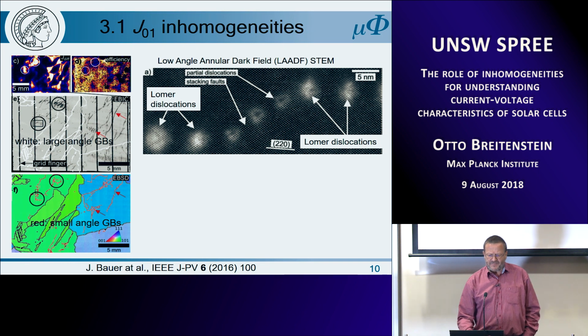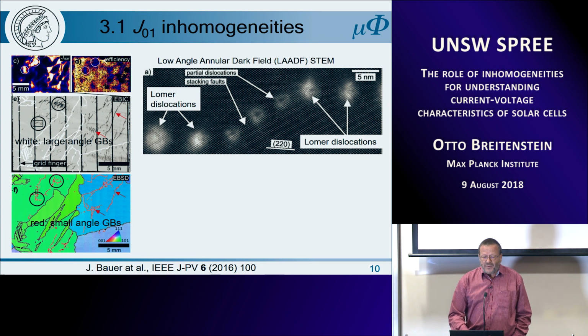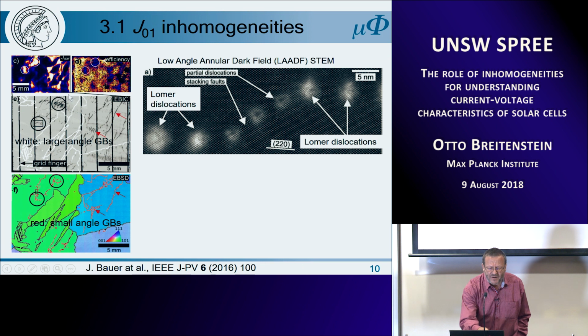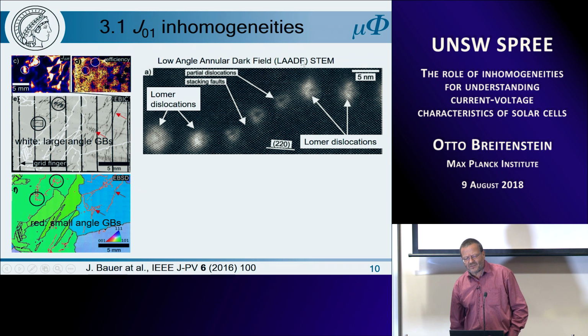And in these boundaries, we have prepared a number of samples, actually 6 samples, I think it was, from 2 grain boundaries, and we have performed so-called low-angle annular dark field, LAADF, scanning transmission electron microscopy.